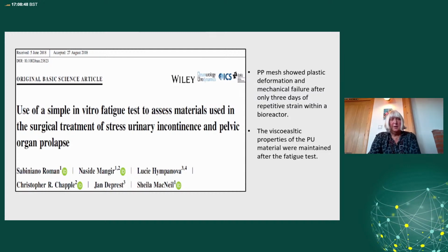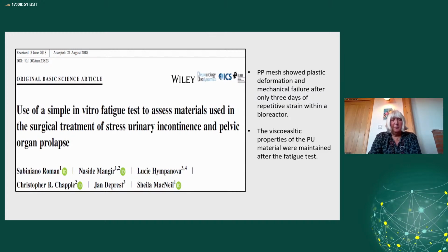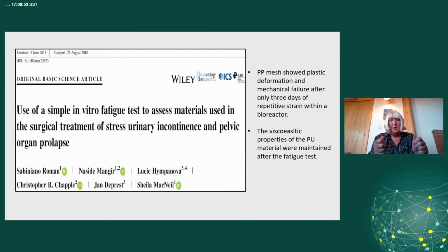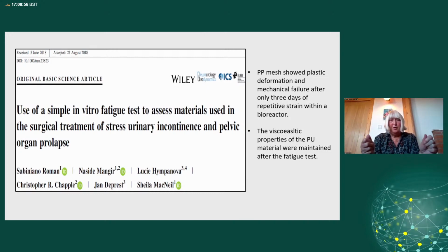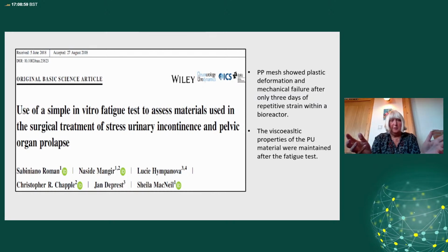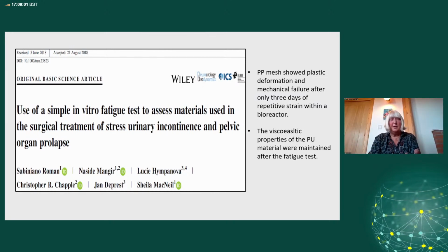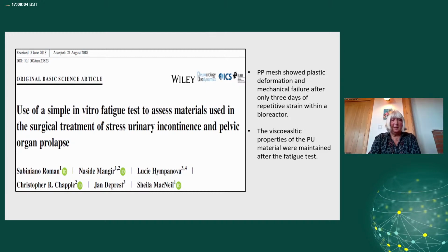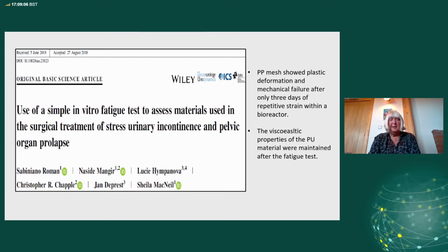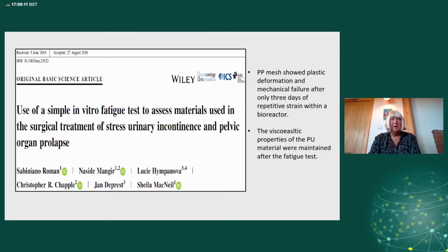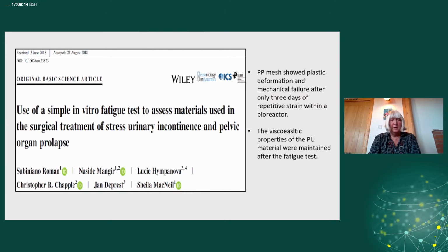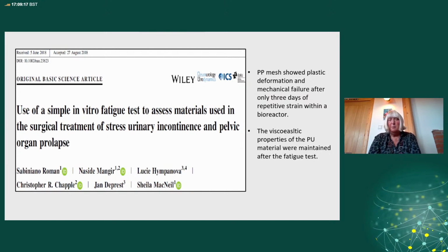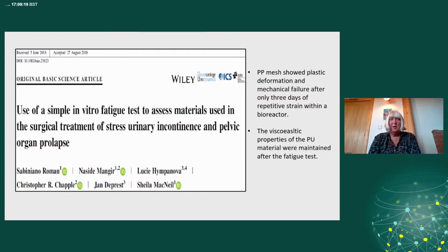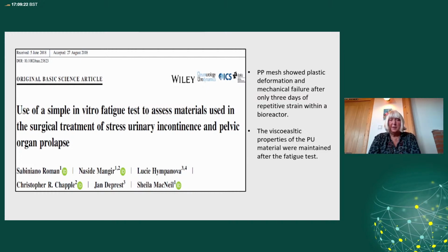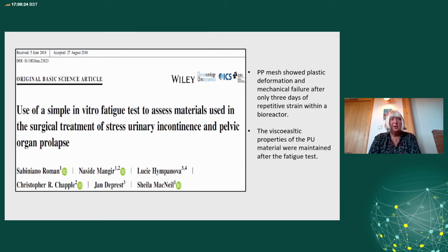Now, a simple test that we developed was to simply take some of the mesh that we had made, clamp it, stretch it by 25% every few minutes for 3 days, and then let it go. And then look at its mechanical properties post-testing. So we have this very simple fatigue testing. It's only 3 days. It's nothing like what the material must have to survive when implanted for decades in a patient. But what we found is that the polypropylene mesh deforms irreversibly after only 3 days distension, whereas the polyurethane materials are fine.